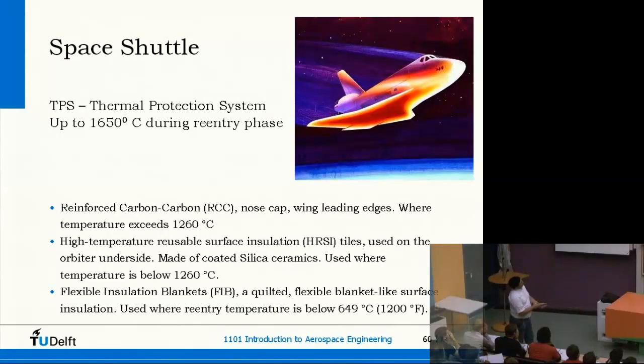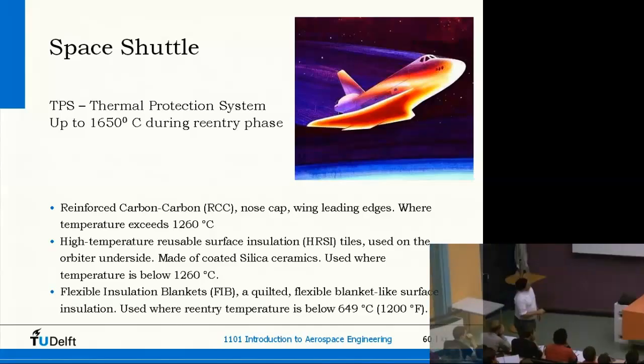This is a heat picture of the space shuttle. Leading edge is here, and also the nose up to 1650 degrees, and that requires special material. For instance, I mentioned already carbon-carbon, reinforced carbon-carbon. Nose cap, wing leading edges, where temperatures are very, very high. But these materials are also very brittle, as we have seen with one of the accidents.